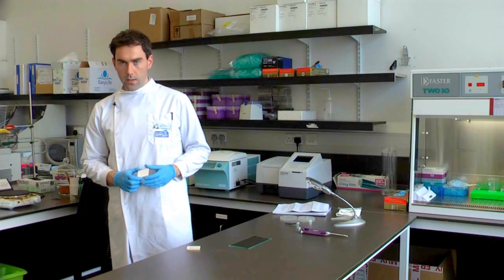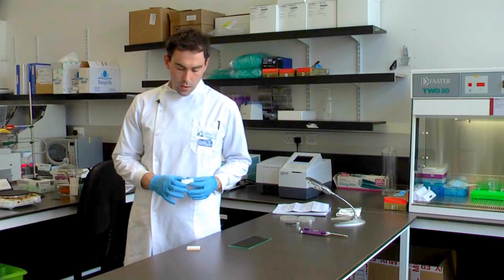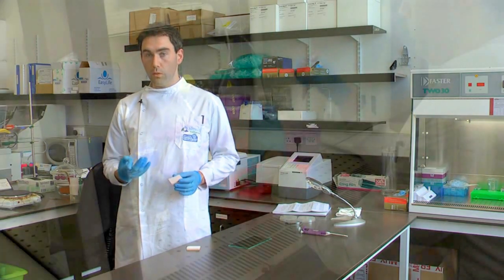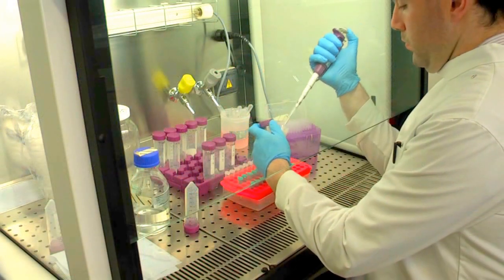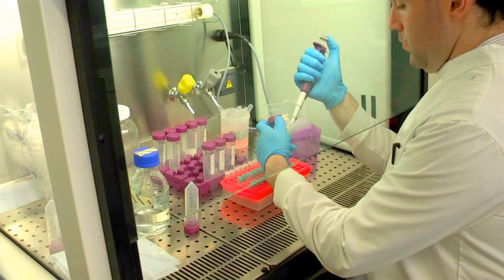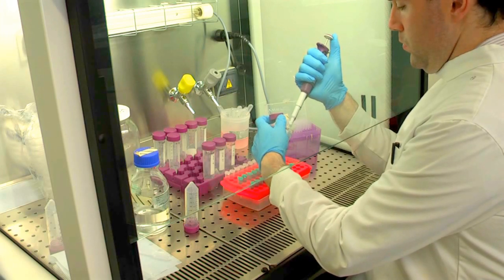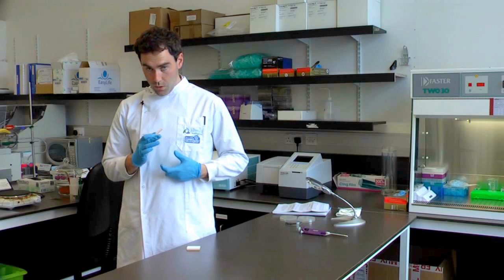In terms of the practicalities of how the test is actually done, a predetermined concentration of bacteria will be grown in liquid solution overnight and this is then placed onto the surface of the ceramic, in this case, or indeed the glass which is of interest.